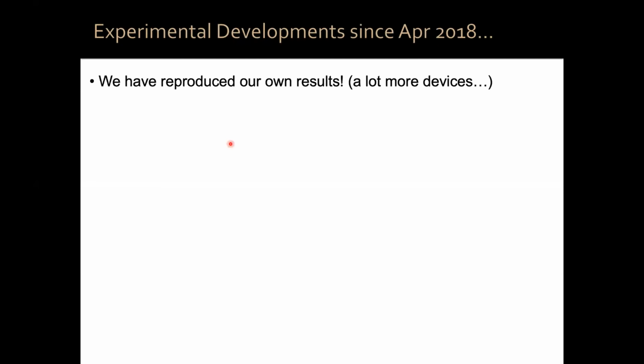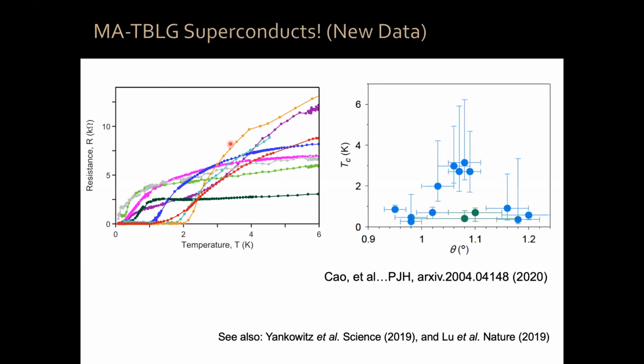The first thing is that we have reproduced our own results. Believe it or not, that doesn't always happen. So it's good when you're able to reproduce yourself. We have since then made many, many more devices. Here is what I told you before. This is TC as a function of twist angle, and we have a superconducting dome between 0.9 and 1.2 degrees.